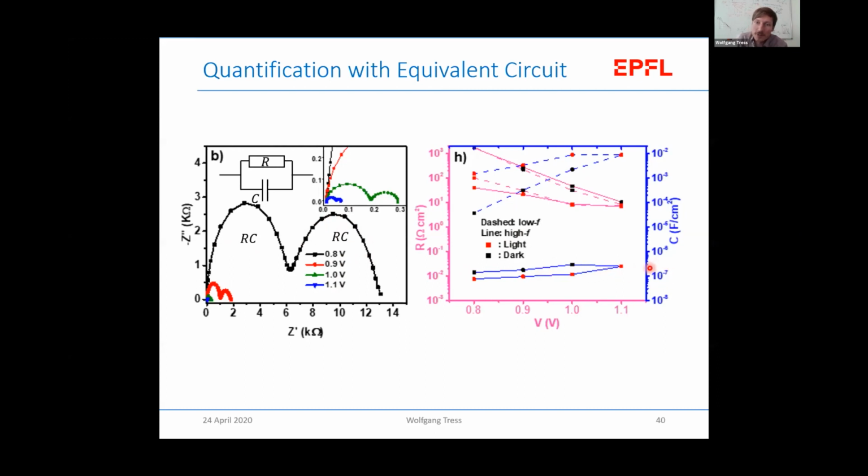This is kind of the geometric capacitance, just the solar cell, more or less the perovskite between the electrodes as a plate capacitor. The interesting point is these dashed lines, there you can see that the capacitance increases by several orders of magnitude when we go higher in voltage, and it is much higher also when the light is on.